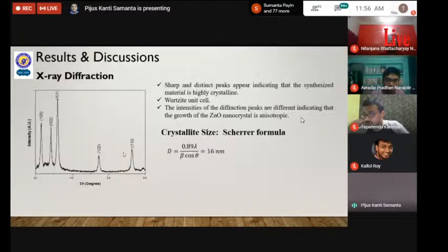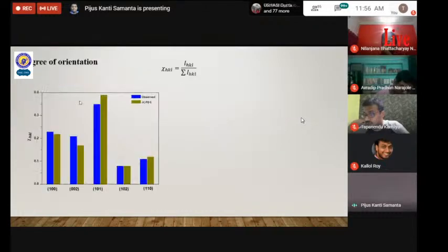And we also see that the intensity of these different diffraction peaks are different, which clearly indicates that the growth rates of various facets of the zinc oxide crystal is different. So we have studied here the degree of orientation, which is basically the fractional intensity of a particular peak to the aggregated intensity of all the diffraction peaks. The blue bars are the observed data and the green bars show the standard JCPDS results. The results are almost consistent except this 101 peak, that is due to the difference in the surface energy of this phase as per the reported structure.